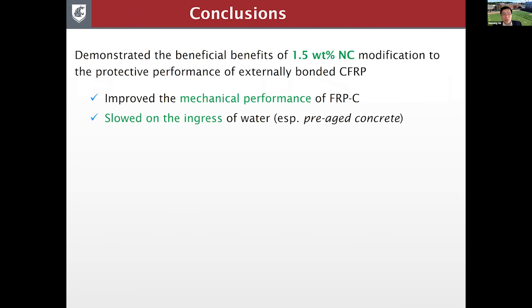So to conclude, this work demonstrates the beneficial effect of 1.5% nanoclay modification to the protective performance of externally bonded CFRP. And basically the results showed better mechanical performance after salt scaling in terms of elastic modulus and compressive strength. And also the nanoclay was able to slow down the ingress of water. The benefit was especially pronounced for pre-aged concrete.